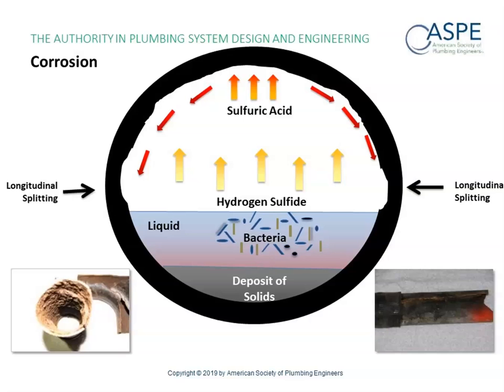The plumbing code tells you that you need to size the pipe according to a fixture unit chart. Well, the fixture unit chart was based on higher flow fixtures. So if you reduce the amount of liquid flowing through a pipe, the media slows down and you end up with a deposit of solids on the bottom of the piping system because you don't have adequate velocity. There's this very smart man, who's long dead, Manning. He came up with a formula known as Manning's formula. What Manning told us is that we are looking for a minimum of 2 to 2.5 feet per second in a piping system in order to keep the suspended solids in the medium when it's passing through. In this case, we're not achieving that velocity, so we have a deposit of solids.